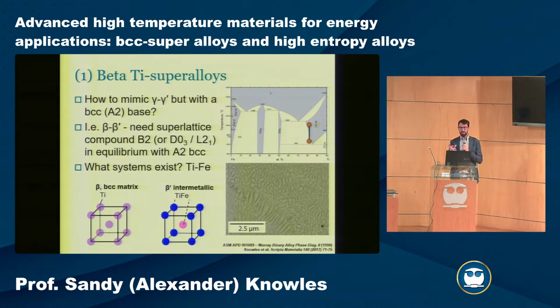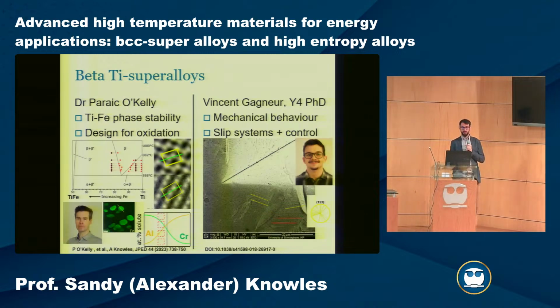In a titanium base, in the titanium iron system, you can have BCC titanium at high temperature in equilibrium with this titanium iron phase, which is an ordered BCC intermetallic. And so early work from my PhD time, we tried to see whether you could utilize this precipitation reaction. And then Paraic and Vincent, who have been PhD students with myself, have been digging into the system in greater depth.